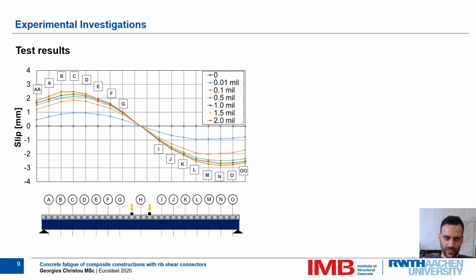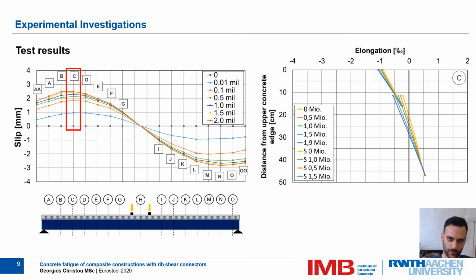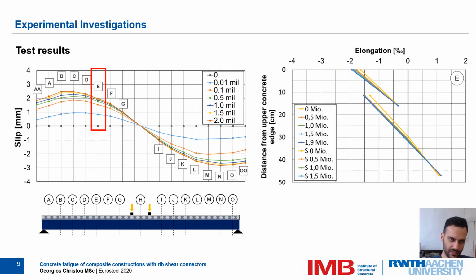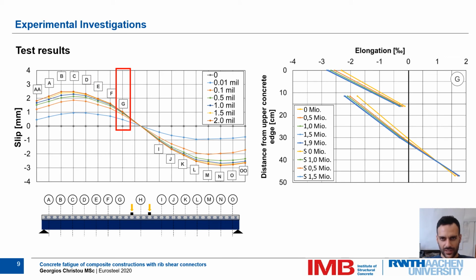By means of the elongations measured over the height of the girder, it is now possible to calculate the shear forces which are transferred between the sections. These measurements were performed in every fourth dowel over the length of the girder, for example in axis C, axis E, and axis G. Although the dowels provide theoretically a full shear connection, the assumed rigid connection of the composite partners is invalid from the beginning of the test, since slip is required to activate the dowels. This can be observed comparing the elongations of the steel and concrete near the lower surface of the concrete, where a gap is observed between the steel and concrete strain, as seen here in the example of axis G.